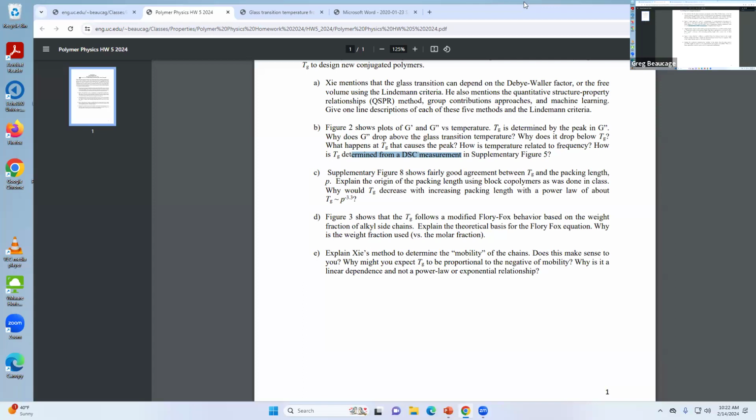Anyway, he's got a DSC down there. Some of his stuff is higher temperature. He might have a DTA. If you're doing metals, a DTA is better because a DSC can't get to such a high temperature. You can't get to 1500 C with a DSC. Also, if you want to do DSC in space, which people have done, then you basically do a DTA because it's much easier. You just have a block heater with two thermocouples and that's it. But this thing needs a computer that servos it and controls the heat flow to match the temperatures, which is more complicated.